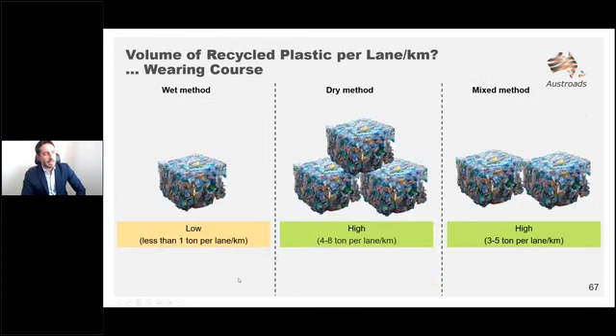The volume of recycled plastics per lane kilometer: how much can we use on a wearing course, for instance, 1 lane, 1 kilometer. So the wet method is obviously low. We are modifying the binder, so we are adding a certain percentage of plastic to the bitumen, which is already like 4 to 6% of the entire matrix, the asphalt mix. So less than 1 ton per lane kilometer. The dry method is the one where you can push higher volumes of plastics into the mix, up to 4-8 tons per lane kilometer. And the mixed method is still high, but kind of an intermediate situation between the two, between 3 to 5 tons per lane kilometer. So that's just a quick look at the volumes that can be used. Obviously, that depends on the mix design and a lot of different other factors.